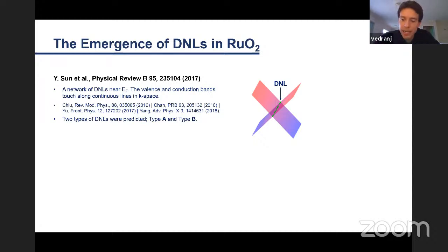It's a symmetry-protected crossing of the conduction and valence band along a continuous line in k-space, and it has relativistic fermions close to the crossing point where the two bands meet, and they are typically protected by crystalline symmetries. In particular, they emerge in systems with inversion, non-symmorphic, time reversal, and mirror reflection symmetries. And they force this protected crossing of the conduction and valence band in k-space. There are essentially two types of Dirac nodal lines in ruthenium dioxide, a type A and B.